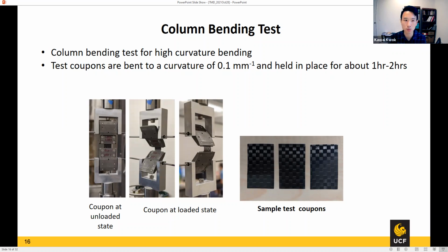and you easily just overshadow that with noise. Because the four-point bending test does not have a clamped edge, a lot of vibration and a lot of noisy data come out. So that's one reason. The other reason is that the curvature you can get to is a lot higher in this test. So basically, in the column bending test, you clamp the material inside the fixture and apply the compression force. Because that compression force is slightly offset from the sample, you create a bending moment.